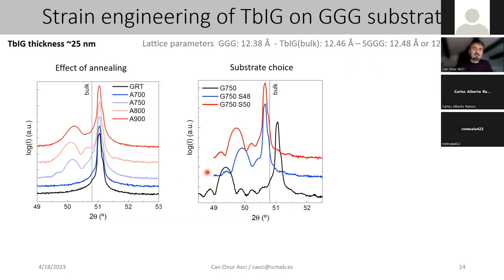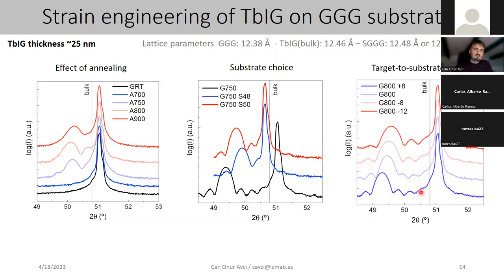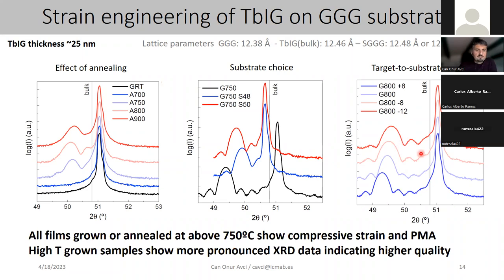We also studied the target to substrate distance, basically changing the distance between the material from which we are sputtering and the substrate that we are sputtering onto. And that also did not show much influence, just a slight change in the strain state. So this concludes that all films grown or annealed at about 750 degrees Celsius show compressive strain, and they should show perpendicular magnetic anisotropy. The films that are grown at higher temperature, rather than grown at room temperature and then annealed later, show basically more pronounced XRD data, indicating higher quality.